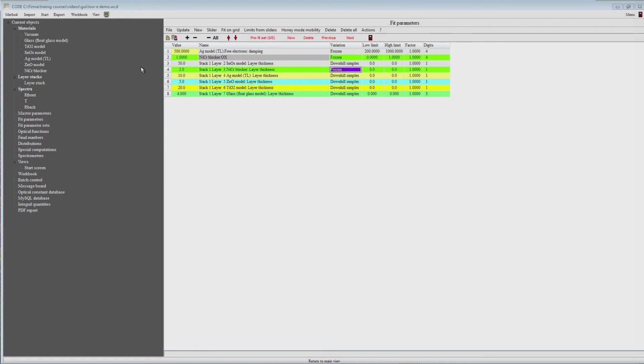That is not a thickness that we can freely vary, because its function is to protect the silver. So we need, let's say, the 2 nanometers, but not more. That function requires a certain thickness which should not be changed, or which is not available as a free parameter for the design.